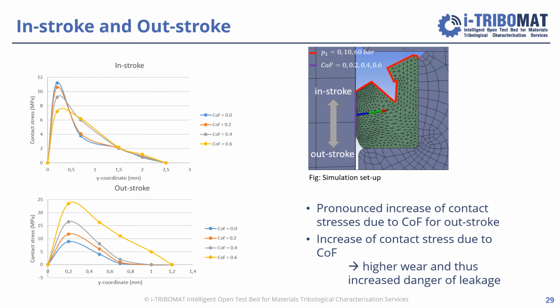So the effect is more pronounced in the outstroke, but qualitatively for both modes, we have an increase of the contact stresses on the average level due to the coefficient of friction we extract from the experiment. And this leads to, in the end, higher wear and thus an increased danger of leakage. But note, we determine the wear and the coefficient of friction separately. They are not linked by a physical model. So whatever the test gives us, that's what we take here.